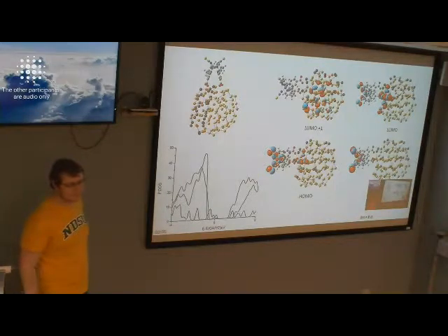First. Second, I suggest you do calculations of the optimized dye, and also of the dye taking exactly the structure you have from cutting it off the quantum dot, with the structure preserved as it was when attached, not the optimal one. Because some conformation, which probably still happens due to the surface, might also affect this change in the gap of the dye.